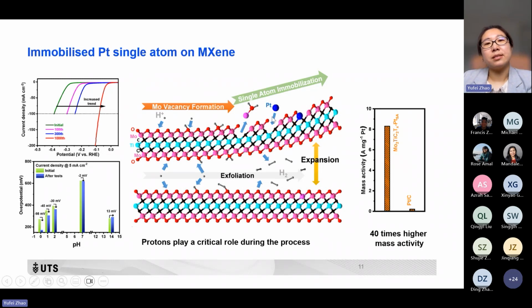And when we utilize this single atom catalyst for HER, we can see the mass activity is really high. It is about 40 times higher than the commercial platinum on carbon. That means we can greatly reduce the usage of platinum, but still keep very high catalytic activity for the HER process.